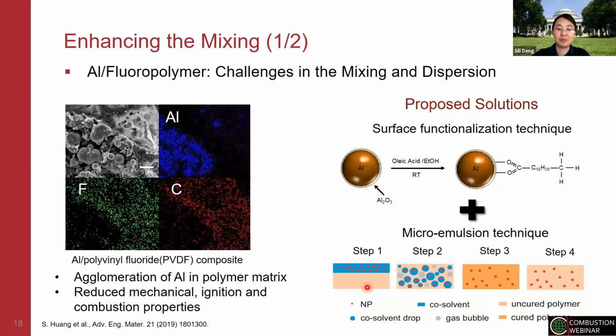And because of the micro-emulsion, you can see that the aluminum particles are monodispersed in the solvent. And later on, when we cure the polymer, you are expected to see a better distribution of the aluminum inside the polymer matrix.